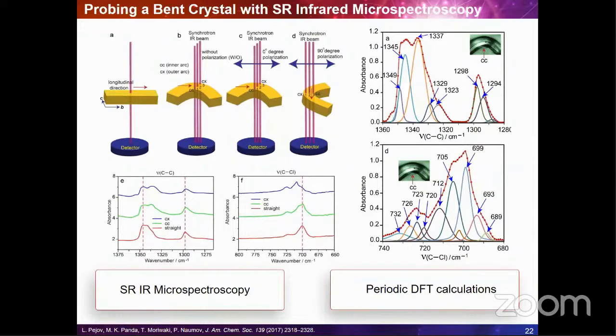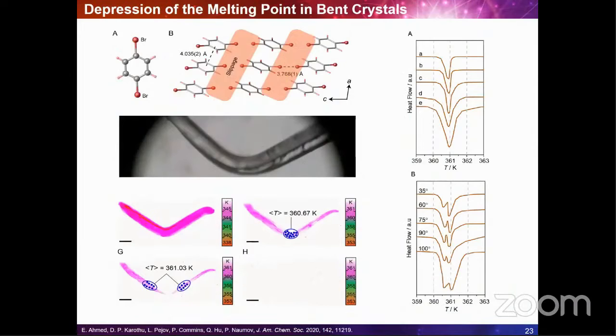induced, one can use this approach basically to generalize it and to apply it to other mechanically, photochemically, or thermally bent crystals. A side result of this analysis was actually the observation that organic crystals can decrease the melting point when they are bent. So as you all know, the melting of any pure crystalline material at constant pressure is one of the most fundamental properties, and it has been used to identify organic compounds or to verify their chemical or phase purity since the early times of chemistry.